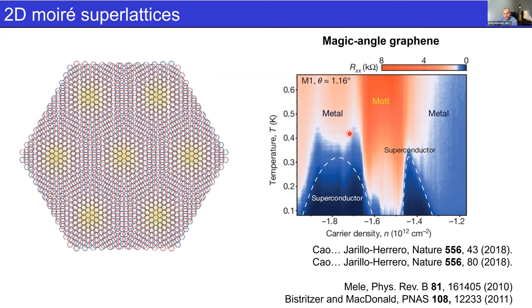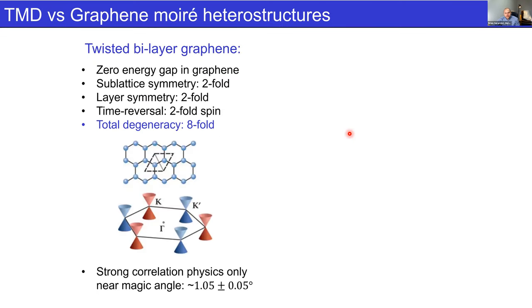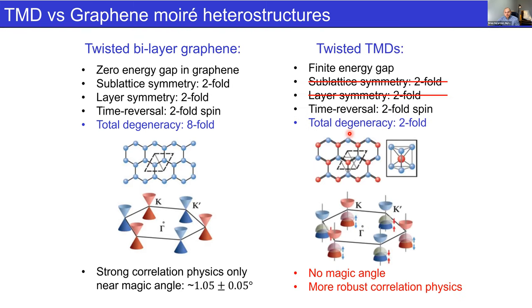I guess what's compelling about the TMDs is that essentially it boils down to simplicity. So we have a much simpler band structure. For instance, the total degeneracy is only twofold. And the end result of this is that, at least for a heterobilayer, there's no magic angle. Whereas in graphene, you need to be quite precise in creating the twist angle to observe the strong correlation physics. In the TMDs, as long as there's perhaps not reconstruction of the Moiré lattice, which happens when you're very nearly aligned, especially if there's an annealing step, then there is no magic angle to observe the correlation physics.